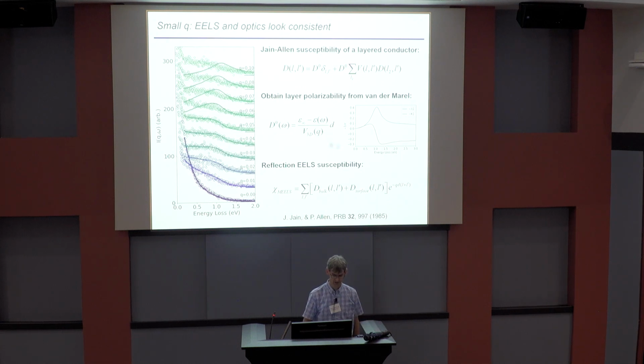So you can take D naught from optical data, and we did this from Dirk van der Marel's data. Then you can plug it in here and calculate the EELS cross-section with it and compare it to the data. D naught, of course, is only measured at Q equals 0 in optics, but you can just say, let's pretend it's Q independent and compare it to the EELS data at different momenta and see what we get. The lines are actually taking the optical data, putting it through the Jain and Allen machinery, putting in the EELS matrix elements, and then plotting it on top of the data.